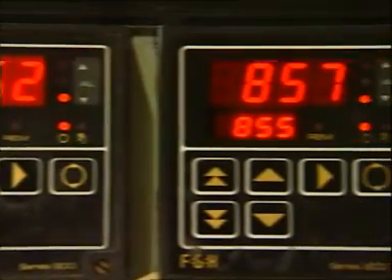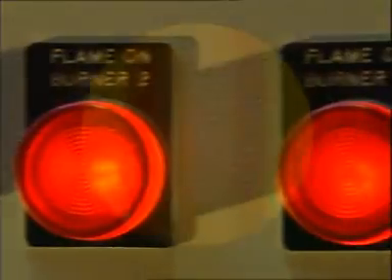The fusion process is carried out in a tunnel furnace nearly 100 meters long and divided into 5 temperature zones, ranging between 700 and 860 degrees Celsius. The glass coating melts, fusing with the steel and forming a permanent and powerful bond. The smooth surface is resistant to most chemicals and tough enough to withstand abrasions and extremes of temperature.